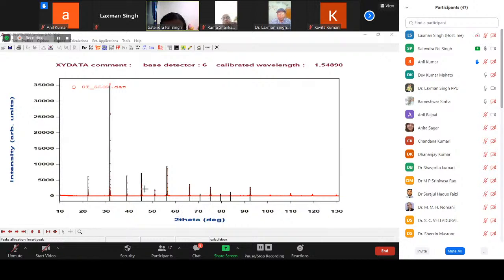Next you have to verify all the peaks. See, like this is 100, and the 2 theta is around 22.262. All these peak positions, how many peaks were there? 1, 2, 3, 4, 5, 6, 7, 8, 9, 10. All are indexed. The first is 100, next is 110, after that 111, 200, 210. So all of these you can get here.